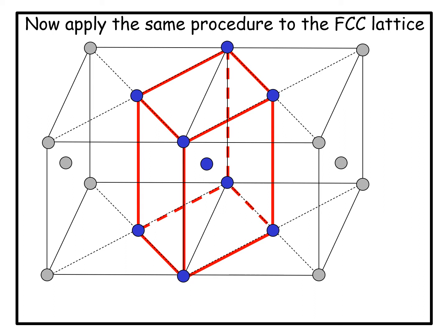Note that if we are working with the original face-centered, then the original face center of the common face now becomes the body center of this new red unit cell. Then we come to the surprising conclusion that face-centered cubic should also be called tetragonal I or body-centered tetragonal.